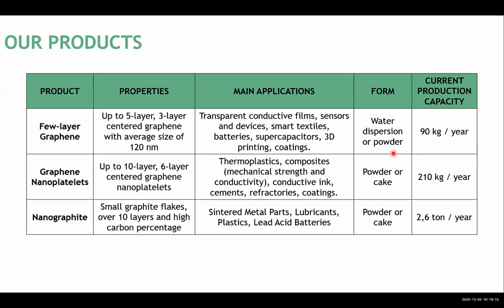Okay, so the graphene products, we have this few layer graphene. So this is up to 5 layers, centered in 3 layers. The production here is 90 kilos per year right now. The graphene nanoplatelets, so it's up to 10 layers, centered in 6 layers. So this comes out as a powder or a cake. This comes out originally in water dispersion, but we can dry it, okay? And this is 210 kilos per year. And the nanographite, so this is small graphene flakes finally exfoliated, 10 layers and higher. So this comes as powder or cake, and this is 2.6 tons per year.